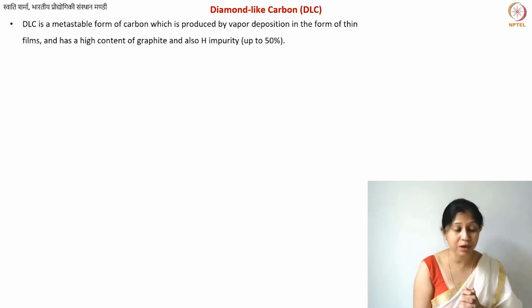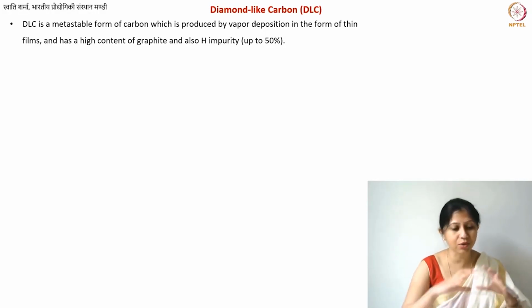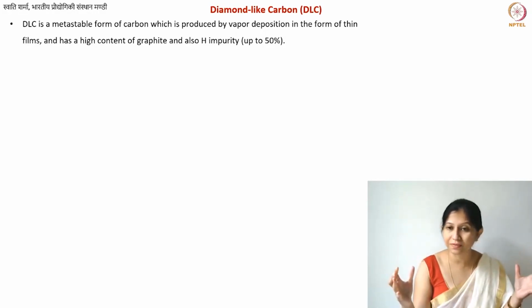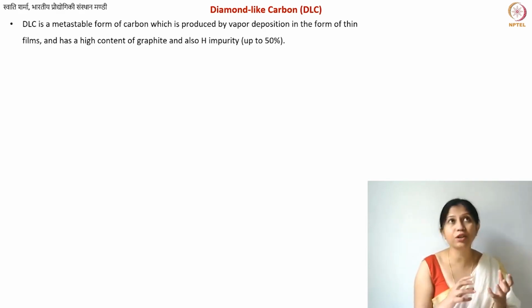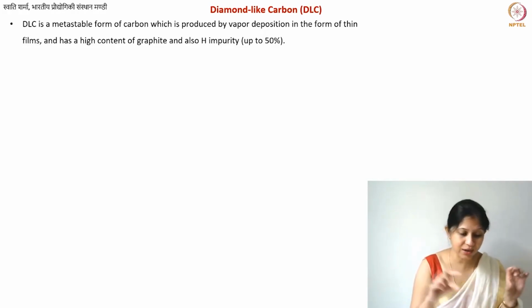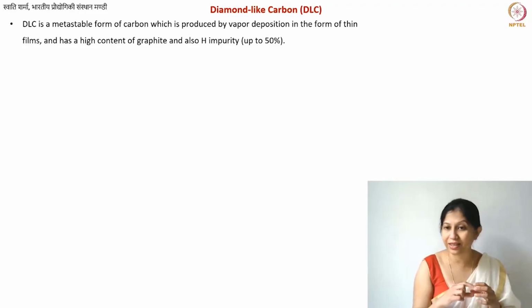So this is sort of a mixture of graphite and diamond. Even sometimes people show this kind of material on the phase diagram of carbon, because even though you have nanoscale crystals, you're always looking at the material as a bulk material, as coating material, and this is something between diamond and graphite. So you have at the nanoscale both diamond and graphite crystallites, and as a result, overall this material behaves like an amorphous material. So physically this is an amorphous material.